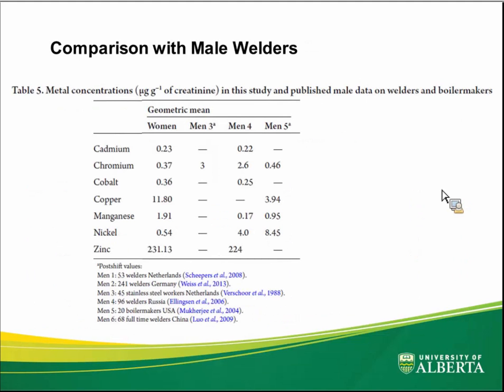So we would expect, if the distributions are similar, that we would have about 5% of the women exceeding this 95th percentile. And what you can see immediately is that for chromium and manganese, we had large numbers of women that exceeded this. And for manganese, almost all of the women exceeded the 95th percentile. So this tells us that it looks like, for chromium and manganese at least, this group of women had very high levels, and for the other metals, we then looked at whether these women had higher levels if we compare them to male welders.